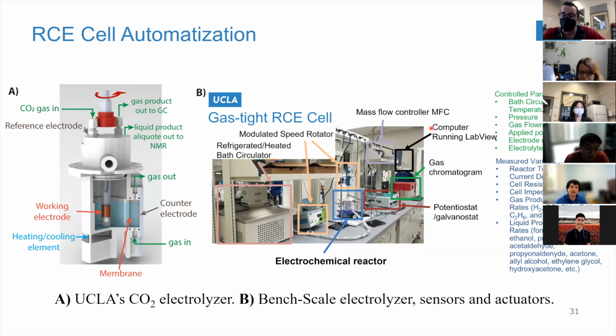Right. So we're just planning now with the rotating cylinder. The geometry is probably as good as it will ever get. So we're working on developing a cell so we can do electrochemistry with rotation of a cylinder at high temperatures and high pressures, because we think that those conditions are actually relevant for industrialization of any of these processes. And what we're also working on is, I showed the data today for flat copper, but we can also put nanostructured copper, with different porosity. And by controlling the external mass transport, we can decouple external mass transport, molecules coming from the bulk to near the surface of the catalyst, and also mass transport inside of the pores.